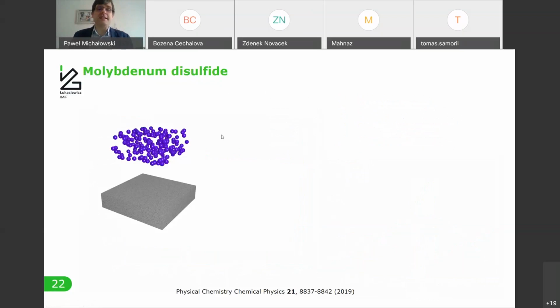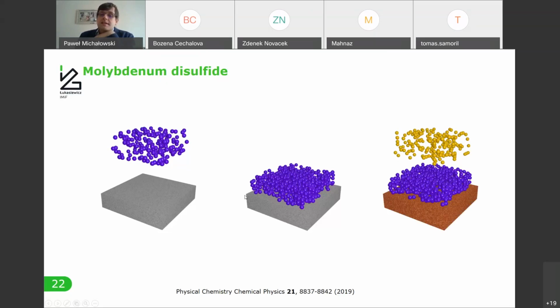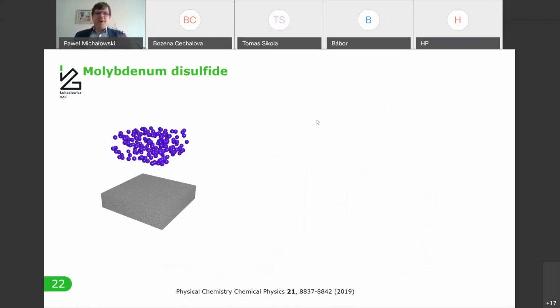And now let's switch back a little bit to two-dimensional material in terms of molybdenum disulfide. So we made a very simple process how to produce this material. First, we simply sputtered some molybdenum on a substrate. And then we use a high temperature sulfurization process to obtain molybdenum sulfide. But then from SIMS, it turns out that the type of a substrate has a huge impact on the quality of the material.